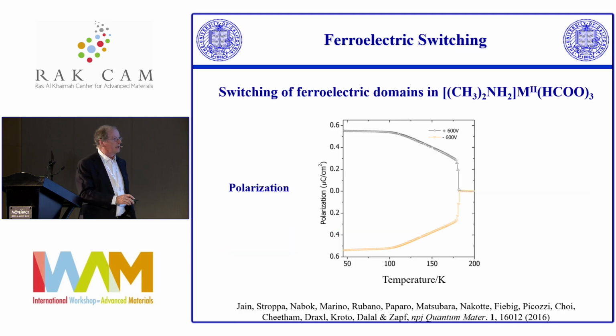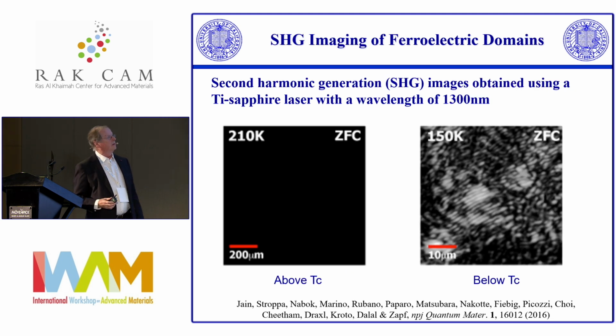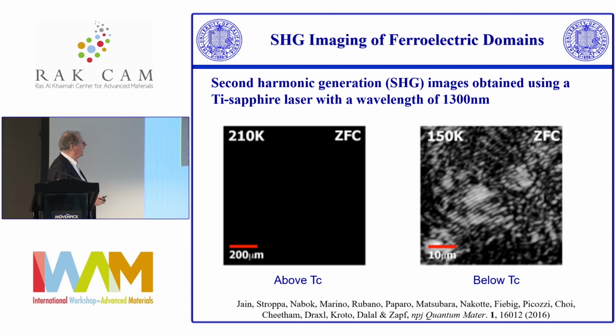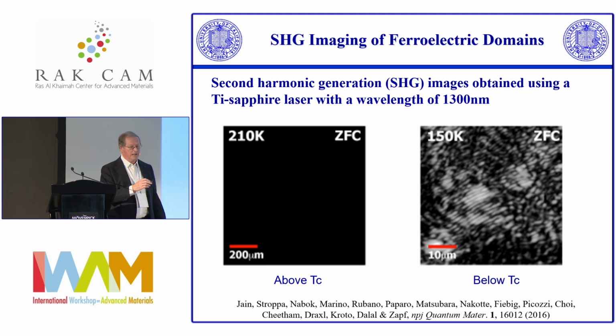It is a ferroelectric. It does all the things that ferroelectrics should do, so if you reverse the polarity of the electric field, then you switch the polarization, as you can see here. And so this is ordering at about 160 Kelvin. And you can see also, this is an SHG imaging above and below the phase transition. And you can see the non-centrosymmetric structure in the low temperature phase from the second harmonic generation using a Ti:sapphire laser. So it's a nice experiment. They're not easy to do.